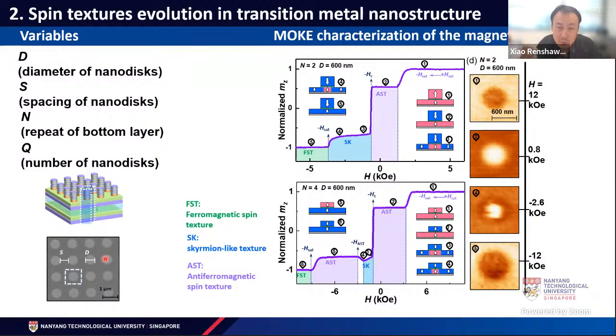To characterize the magnetic properties, we first use MOKE, which is an optical technique, to study the magnetic features. You can see that when we sweep the magnetic field, for example, from positive 5 kOe to negative 5 kOe, or slightly larger, there are multiple features that appear. Let's talk about N equals 2, which means the bottom layer repeats 2 times, and D equals 600 nanometers, meaning the diameter is 600 nanometers. You can see that the ground state can slowly convert into an antiferromagnetic state, then to a skyrmion-like texture or skyrmion-like state, and eventually to a ferromagnetic state.